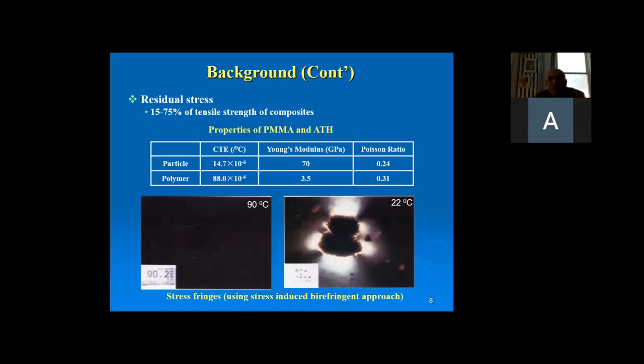Now, here is a picture where we take stress fringes. One is at 90 degrees Celsius, and one is at 22 degrees Celsius when we applied loading in the system. Now, at 90 degrees Celsius the polymer is near glass transition temperature. It doesn't carry much. The elastic modulus of the polymer is near 0.